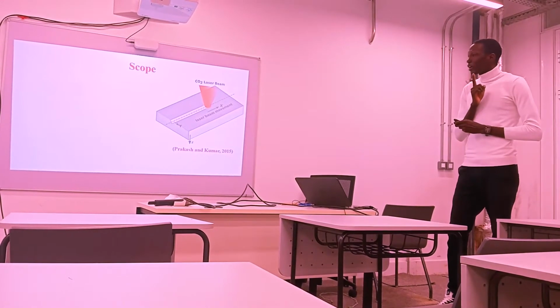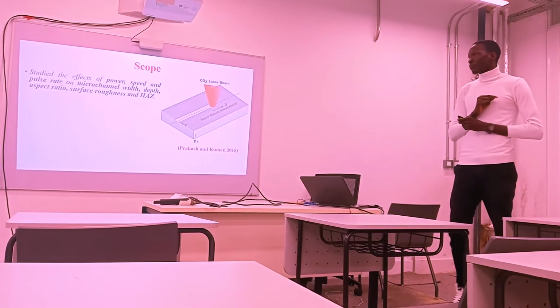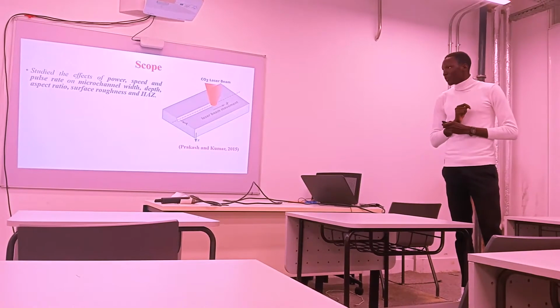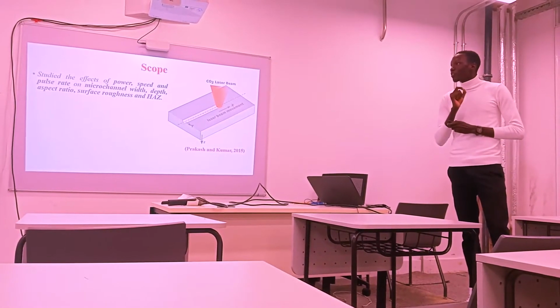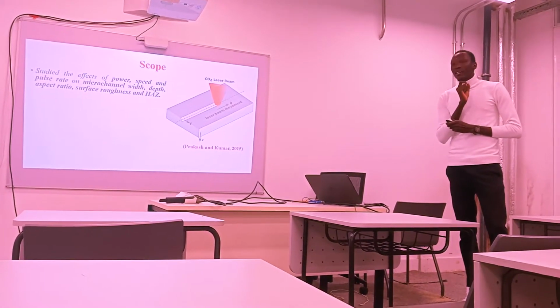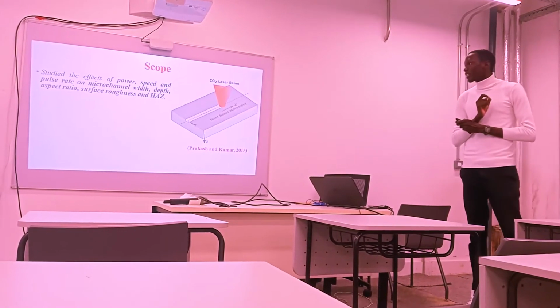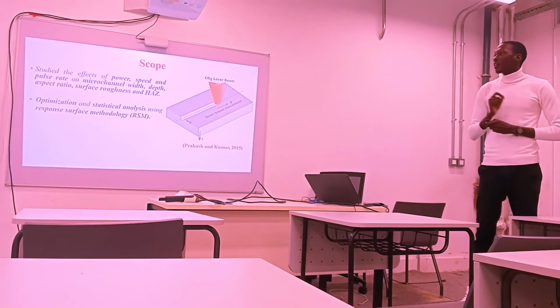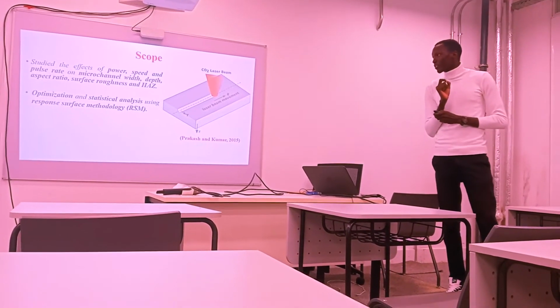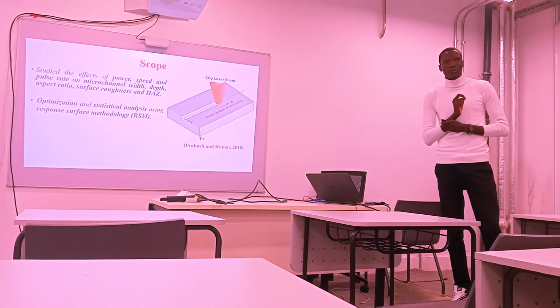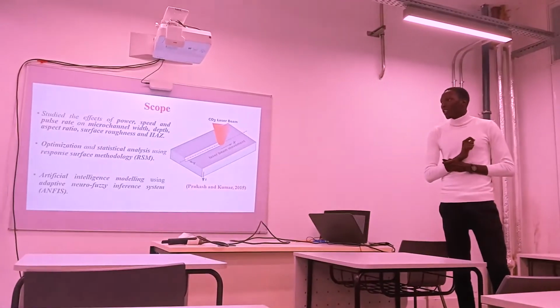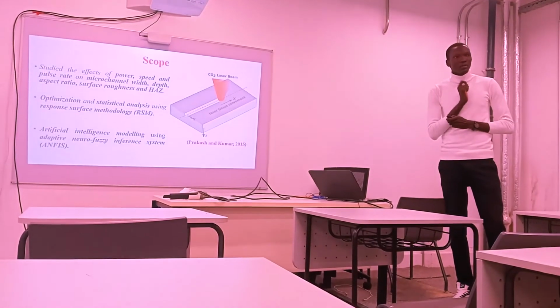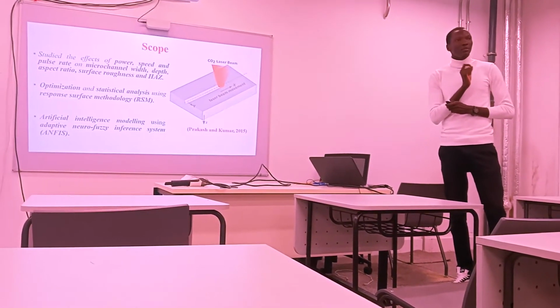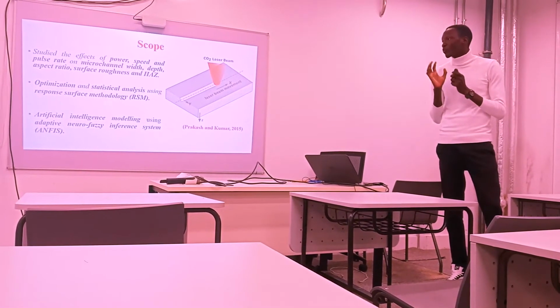Now, what did we do and what did we not do? We studied the effects of power, speed, and pulse rate on the microchannel width, depth, aspect ratio, surface roughness, and heat-affected zone. We also carried out optimization and statistical analysis using response surface methodology. We also did artificial intelligence modeling using adaptive neuro-fuzzy inference system. This is what we did.